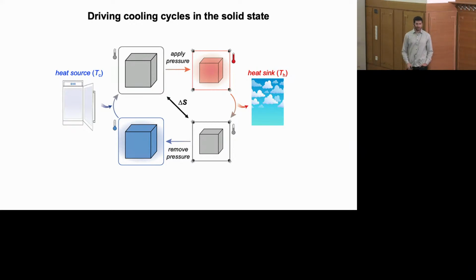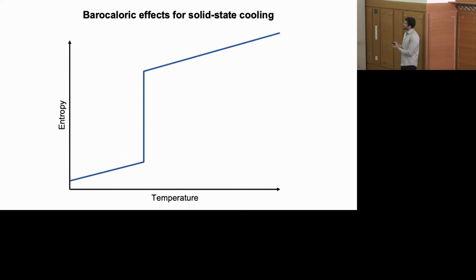And so if you want to think about materials that have large entropy changes under very similar sets of conditions, you typically are going to be interested in a material that undergoes some type of phase transition. And a first order phase transition where application of a small temperature change or application of a small stimulus, like a small increase in pressure, can induce a really large entropy change in a material. And so what you would really like is a material that undergoes some type of first order phase transition between a low entropy, more ordered, and high entropy, more disordered state.